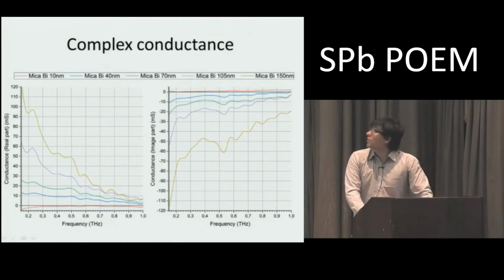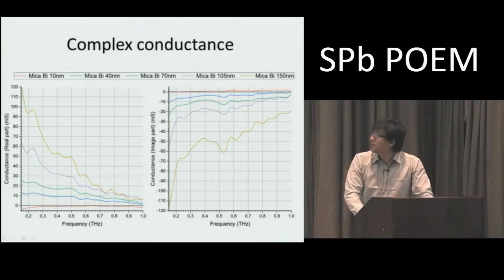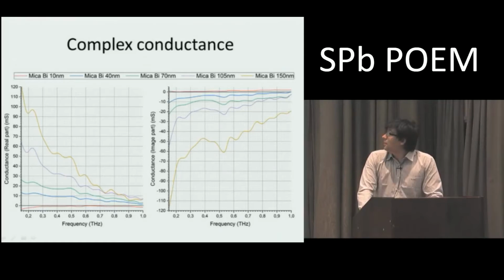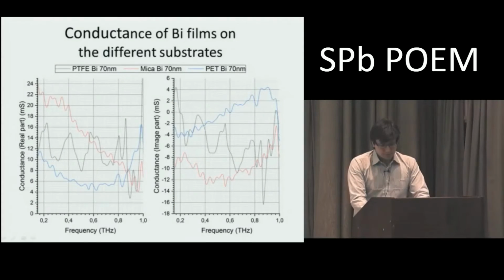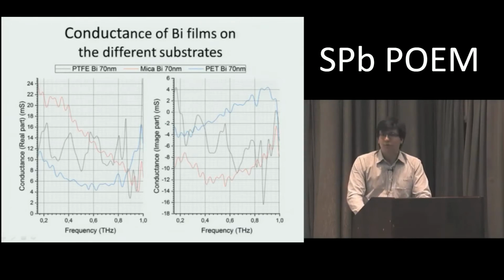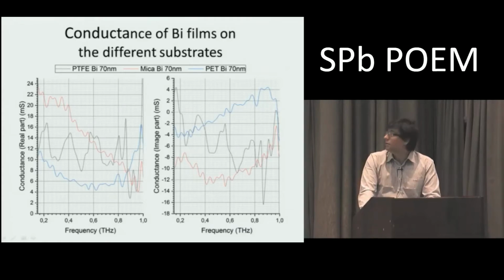Next, we calculated the complex conductance, and we show that with increasing nanolayer thickness, the conductance increases. The imaginary part of conductance decreases. And we also observed different substrates with the same thickness, and we observed that different substrates give different properties of the bismuth layer. So there is very big conductance in the real part for mica, and lower conductance for the PET substrate.